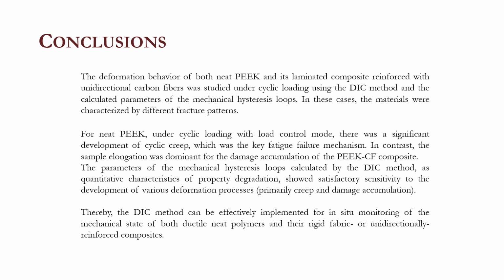In contrast, the sample elongation was dominant for the damage accumulation of the PEEK CF composite. The parameters of the mechanical hysteresis loops calculated by the DIC method as quantitative characteristics of property degradation showed satisfactory sensitivity to the development of various deformation processes, primarily creep and damage accumulation. Thereby, the DIC method can be effectively implemented for in situ monitoring of the mechanical state of both ductile neat polymers and their rigid fabric or unidirectionally reinforced composites.